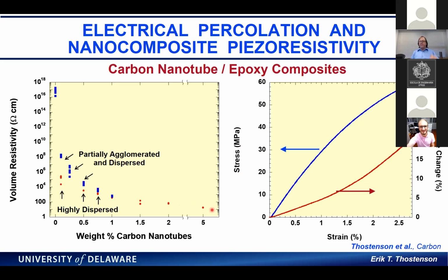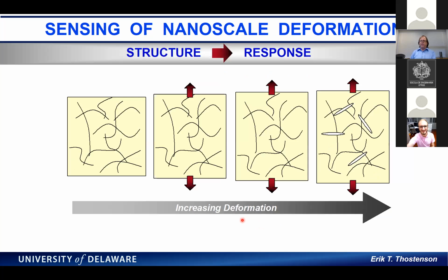So on the right here, this is some of the initial tests we did on these materials. And you can see that with the stress strain curve from the strain gauge, we also see quite a significant resistance change. And I think the reason for this is you can think of all these discontinuous nanomaterials as these tiny little wires. And when you strain them, the tunneling gap changes between those individual wires.